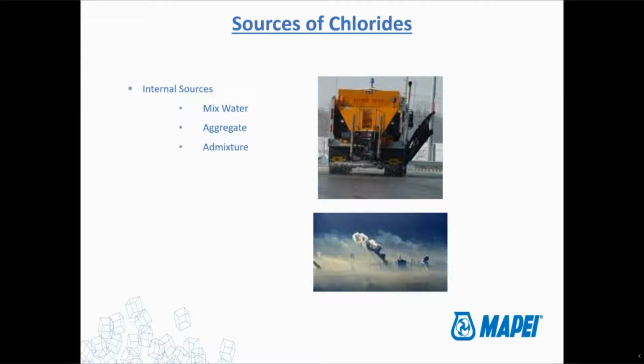And then the third one isn't really an issue anymore, but admixtures. Back in the 60s and 70s, before we had a better understanding of chlorides and how they reacted with reinforcement steel and concrete and the problems that they caused, chloride was actually used as an accelerant. So in the wintertime, when they were pouring concrete, they would use chloride as an admixture just to make the concrete cure faster. So it's very common when you go to older cities.